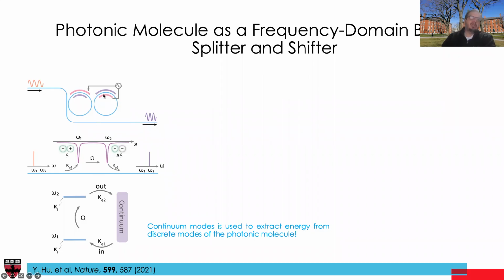So the same topology, same two ring resonators with two RF electrodes. Again, put light in one resonator, apply RF, and now we want to get light out of this resonance. And he found out that if you precisely control this coupling rate, this RF-induced Rabi rate, and this rate, you can find a regime, but not all of these rates are the same, it turns out. We refer to this as a generalized critical coupling condition. The process interrupts itself. Essentially, we put light here, light comes here and leaves the system. So the Rabi rotation cycle gets interrupted, which is exactly what you have in a single-sided modulator.